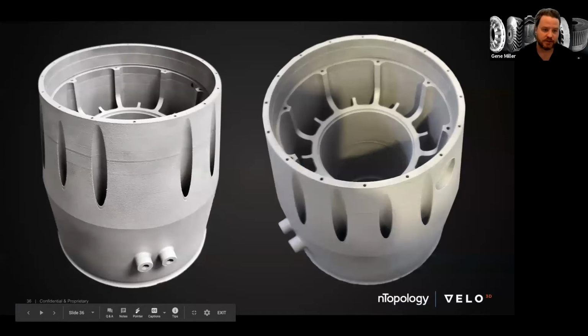And here's the printed part. This is right out of the printer, ready for final machining. This part was about 9 inches round by 9 inches tall. It's printed in aluminum F357. The overall print took just under 3 days. It was close to 5,000 layers.